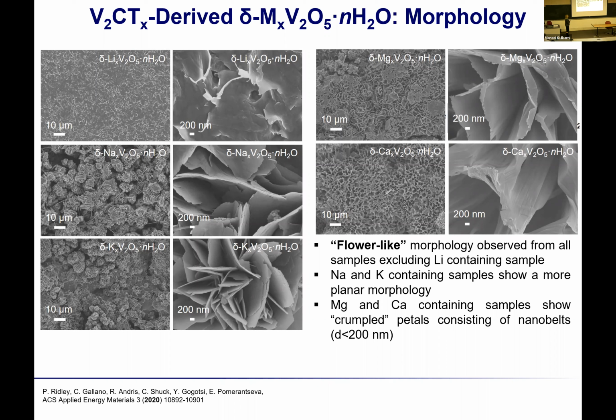So in case of lithium, these two-dimensional plates essentially form a porous layer without agglomeration. But in case of sodium, potassium, magnesium, and calcium, these two-dimensional plates grow together, forming flower-like morphologies. In case of sodium and potassium, the petals in these flowers are flat, straight. And in case of magnesium and calcium, the petals of the flowers have some curvature and have more intricate patterns. So the nature of the chemically pre-intercalated ion affects not only the chemical composition and structure of the synthesized materials, but also the morphology.